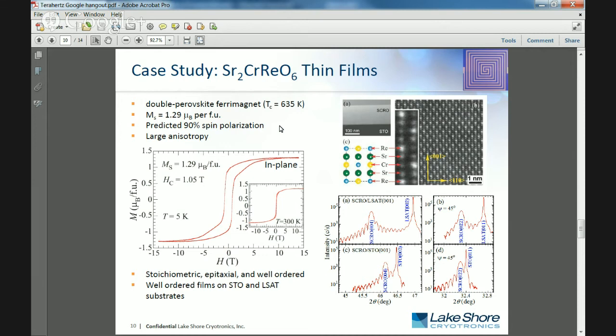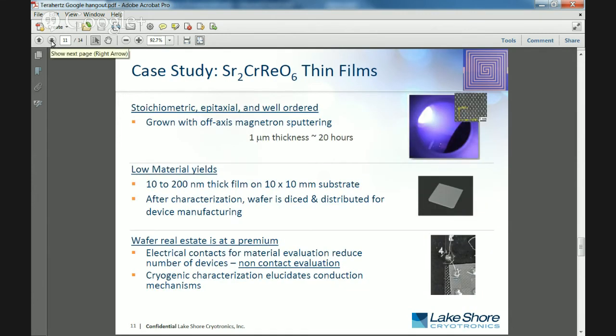And so I would pop over to the next slide and talk a little bit about how these films are made. These are stoichiometric films that are grown on substrates, and it's a very slow process of deposition. A micron thick film can take up to 20 hours. Those materials are grown on small research grade substrates, 10 by 10 millimeter. And after characterization, typically those wafers are diced up and sent to different users for further characterization or even trying to make some devices on them.